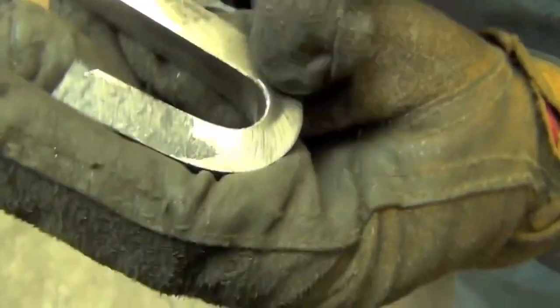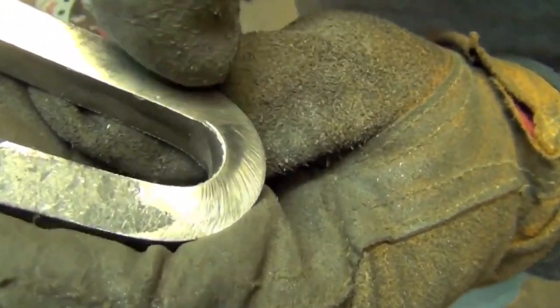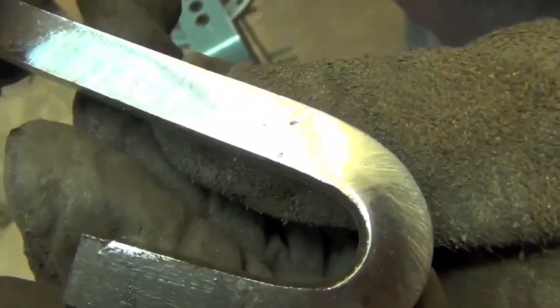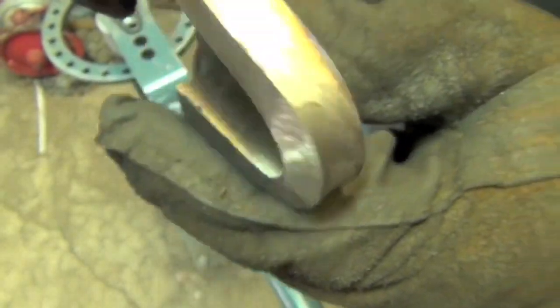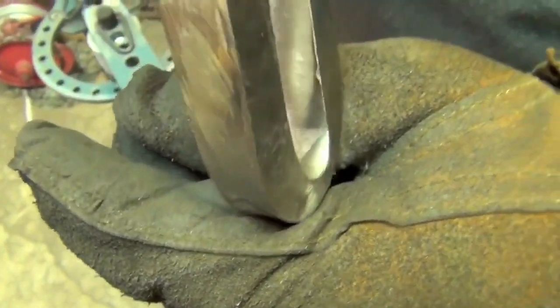And here, this is what I meant with allowable impurities. There's 2 little pinholes, but no crack originated out of it bending. No cracks on the backside. So, most likely, we would have passed the certification test.